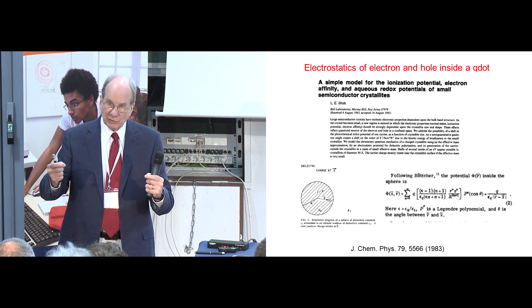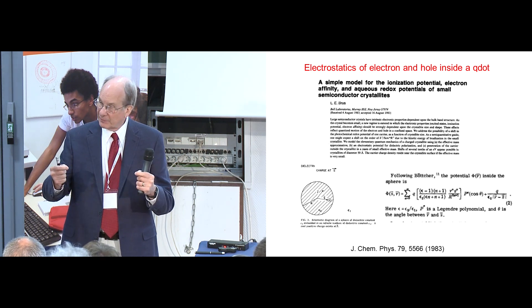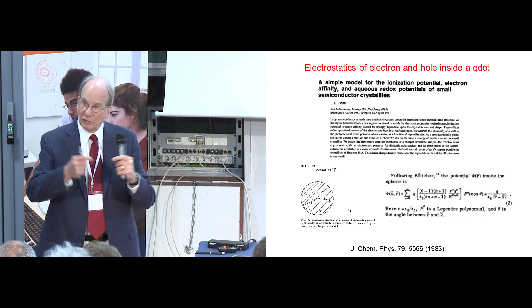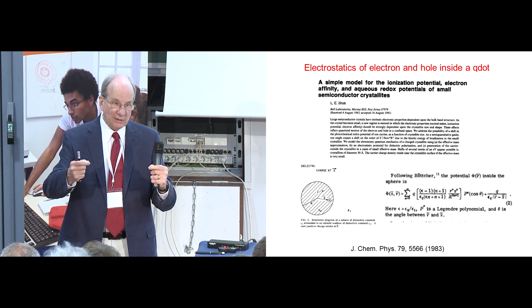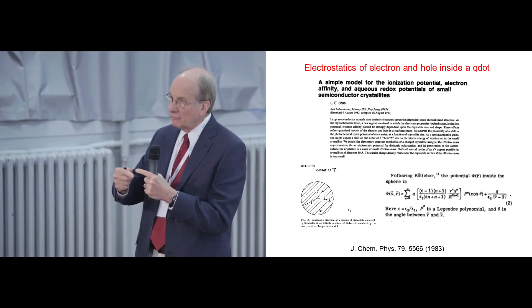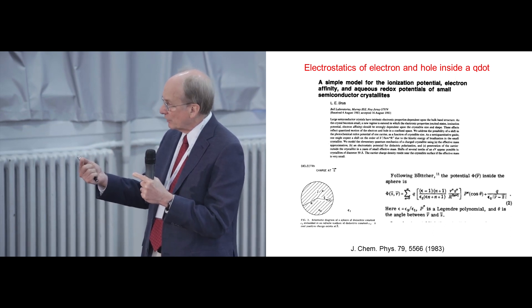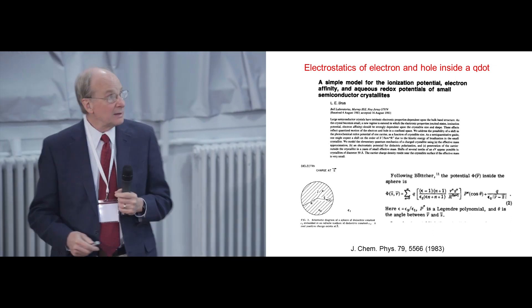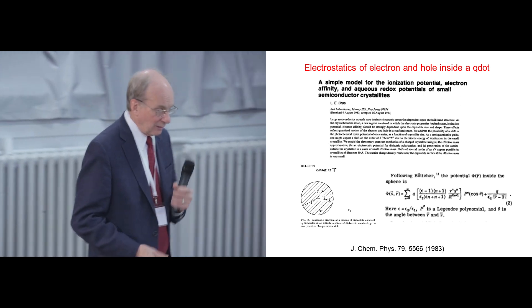We know this is important already just from the bulk solid state physics because in the bulk solid state physics, the Coulomb interaction is screened between electron and a hole in the exciton. And so it follows automatically that if the Coulomb interaction is screened in the bulk material, then the dielectric solvation energy of the individual electrons and holes has to be very important, one by one. So we tried to work this out as well.